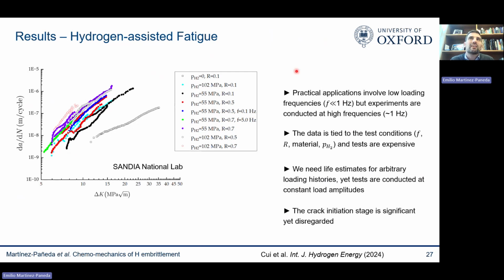One is that practical applications involve low loading frequencies, and there's a frequency effect here. When you load slowly, there's more time for the hydrogen to accumulate, and therefore when we do fast experiments, we're being non-conservative. So ideally, we'd like to do experiments very slow, but we can't, so there's a problem here.